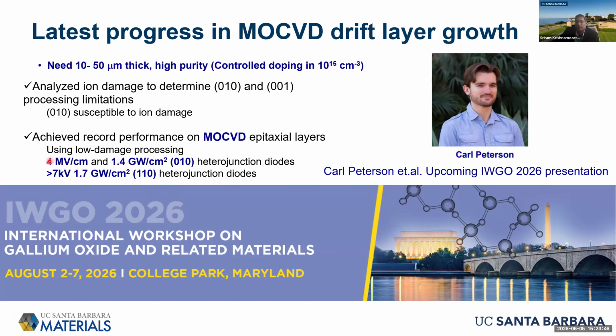So achieving high electric fields at the junctions, up to 4 megavolt per centimeter, translating to a high figure of merit, and also growth along a new orientation of the crystal with high purity, resulting in devices that can block up to 7 kilovolt using MOCVD. To be able to achieve these results, we had to go back and look at the crystal structure more closely and analyze the effect of the orientation on process damage. We also learned that certain orientations are actually more susceptible to ion damage, and so we had to come up with processes that are less damaging. This is going to be presented in a few months by Carl.